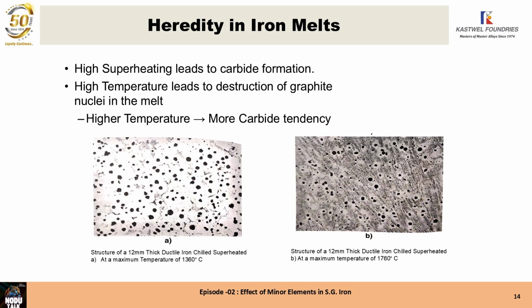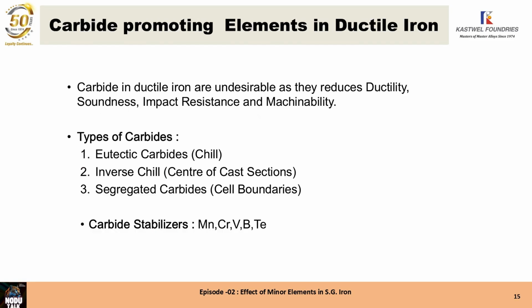Both time and temperature of superheating control the carbide stabilization. So you must avoid unnecessarily superheating the metal and unnecessarily holding the superheated metal at a high temperature. Carbides in ductile iron are undesirable because they reduce ductility, they reduce the soundness, they cause shrinkage in the casting, they reduce the impact resistance of the casting, and they affect the machinability.